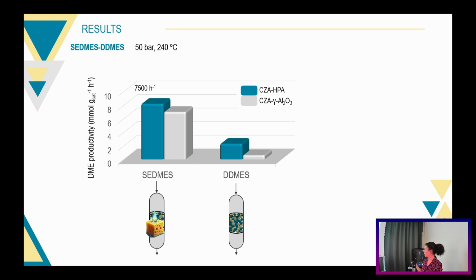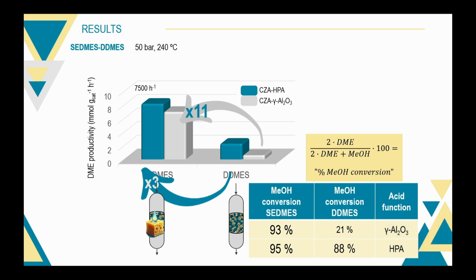When we compare both processes, SEDMES and direct synthesis of DME, meaning with and without water sorption, we can say that the SEDMES process is capable of improving the performance of both catalytic beds, but this enhancement was much higher for the gamma alumina containing bed than for the heteropolyacid containing bed. Where did this difference come from? We calculated this value that can be understood as a methanol conversion for both processes and both catalytic beds. And we observed a huge increase for this value for the gamma alumina containing bed, but not for the heteropolyacid containing bed because there wasn't so much room for improvement already.